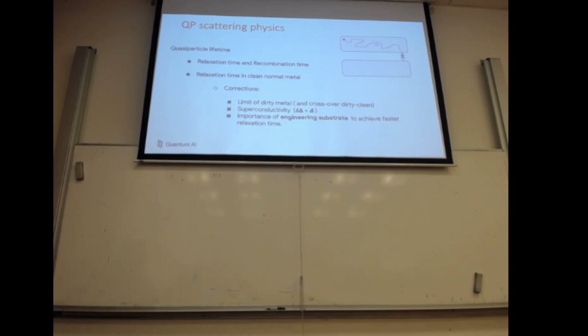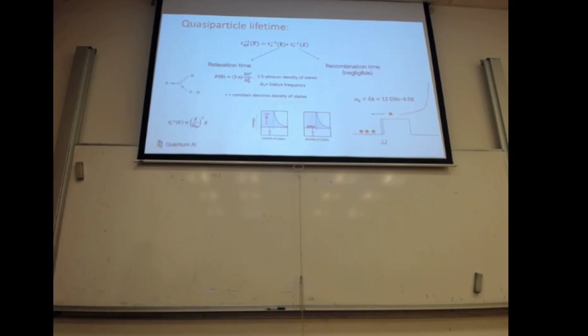So the problem that we need to solve is to see how fast the quasi-particle will relax. Of course, the first question is that the estimates of Kaplan were done with clean metal. Is our metal clean? And if not, how dirty is it? The other thing is that we are interested in energies around 12 GHz, because it's 0.5 Kelvin, so we are interested in energies much below the gap delta. This seems to us crucial, because this estimate should guide us in engineering a substrate that doesn't let the phonon reach the qubit.